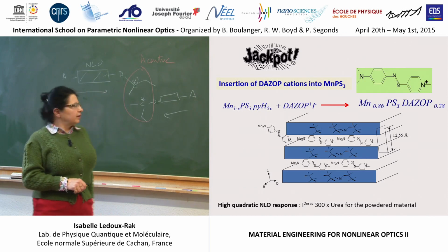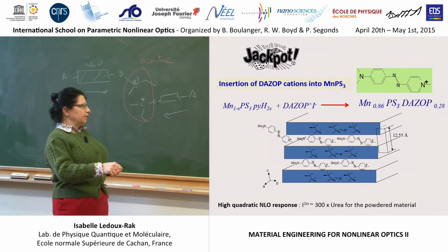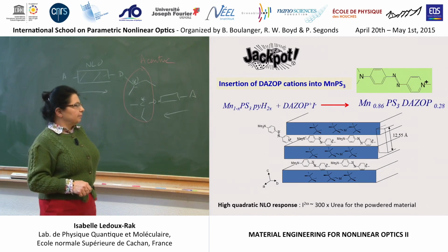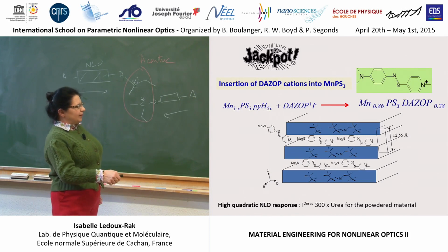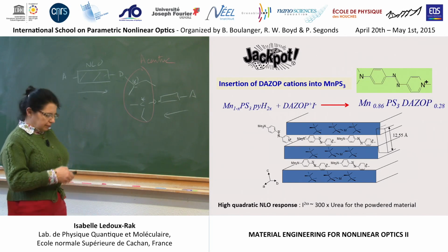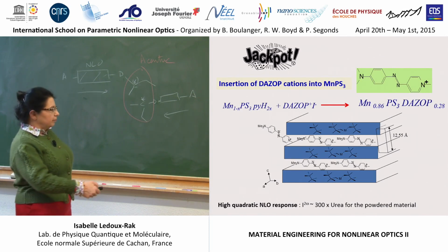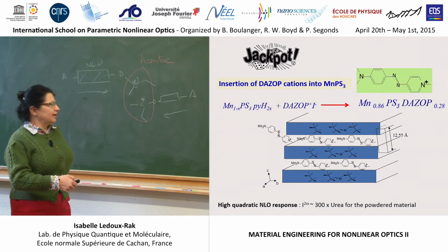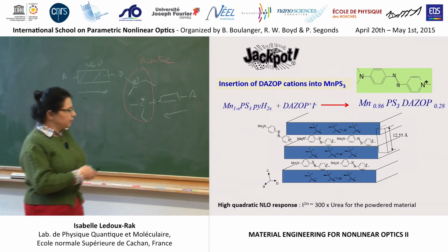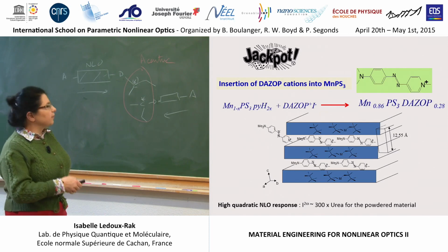And what is found is that all molecules are parallel to each other within each plane and from one plane to another, because you could have a situation where you have parallel molecules in one plane, but if you are not lucky, the next plane will have molecules in the opposite direction. But it's not the case. Everything is parallel, and the high nonlinear response was found a long time ago. But the point was to make sure that molecules are really organized like that, in a parallel architecture, in order to lead to this very high nonlinear response.